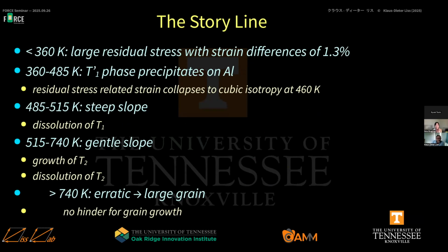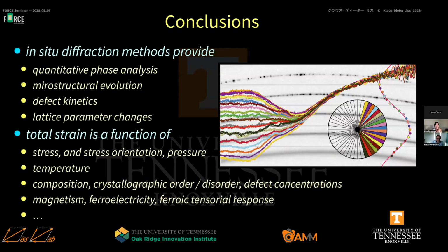So here's a storyline. We get residual stresses at the beginning, and we get precipitation of secondary phases. The residual stresses, they collapse. Then we have the dissolution of the second phase. We get the growth of the second phase and the dissolution of that second phase. And eventually we get large grains due to no hindered grain growth. Okay, we have published that recently. Just look up our newest papers, myself and Dr. Kawasaki.